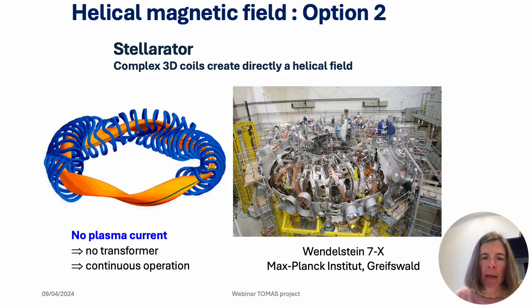developed in parallel. There, the trick is that you get rid of the transformer and you produce this helical twisted field in a different way. In fact, by shaping the coils in this weird shape that you could see, the blue shape here, you produce immediately the right magnetic field with a helical twist. This configuration is the basis of a big machine in the north of Germany, in Greifswald, Wendelstein 7-X, and also there the laboratory has contributions. So this is a different solution for the same problem. We create in both cases a helical magnetic field, and in that way we can confine the particles.